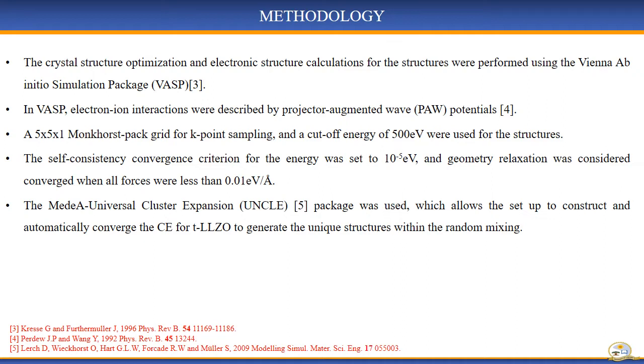The geometry relaxation was considered converged when all forces were less than 0.01 electron volts per angstrom, with the self-consistency convergence criteria for the energy set to 10 to the exponent negative 5 electron volts.